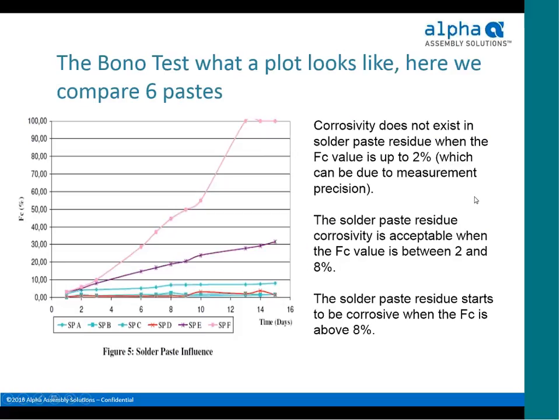The math behind this, there's a corrosivity factor that's calculated based on how quickly the anodes are degraded by the exposure to the flux residue in that bias. One of the things we'd like to stress about this test is that we find that we have a lot of variation when we run the test ourselves in our test results. Alpha actually contracts this out to a lab that's got a much more low variation test process.